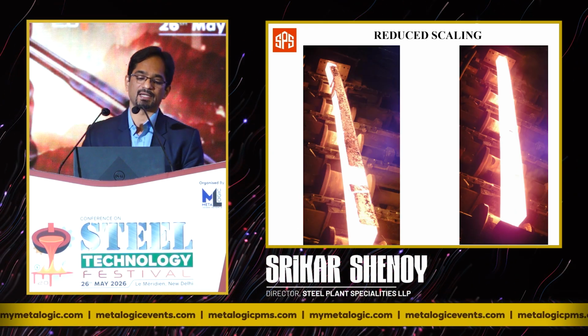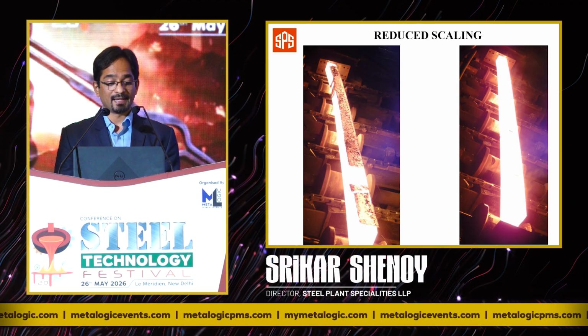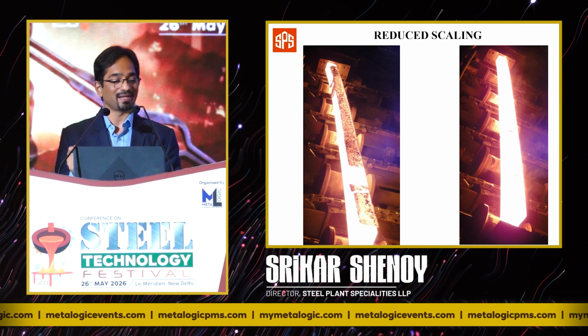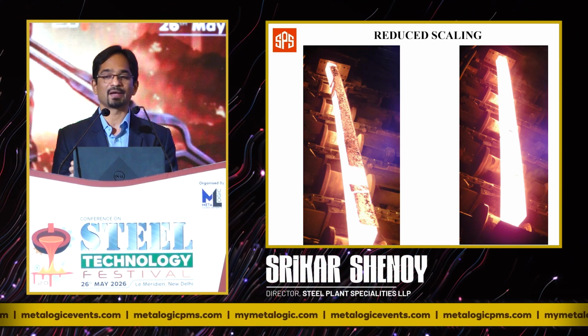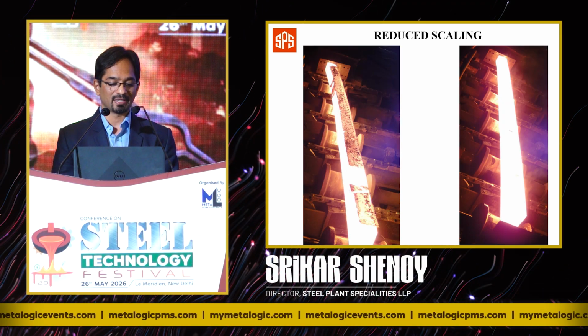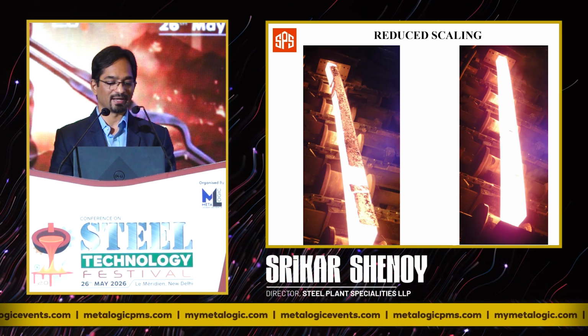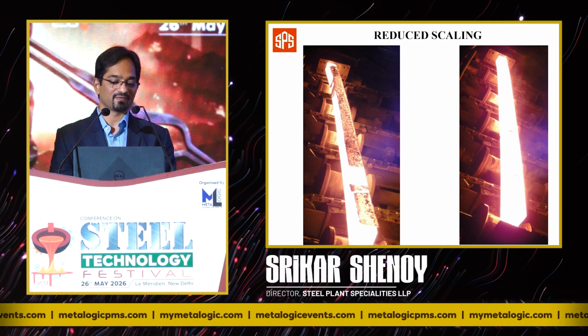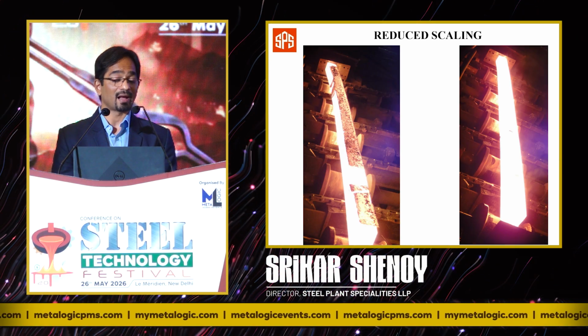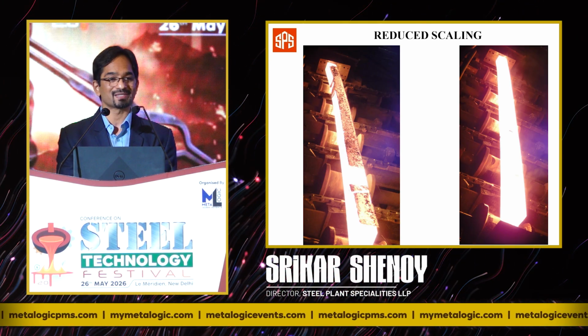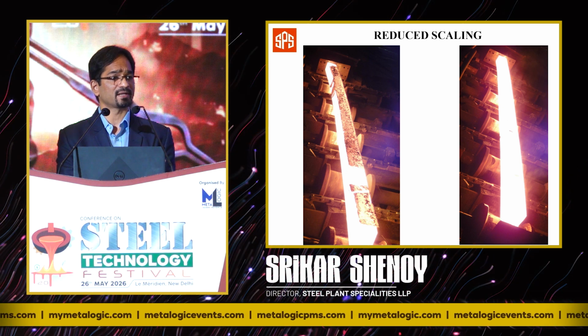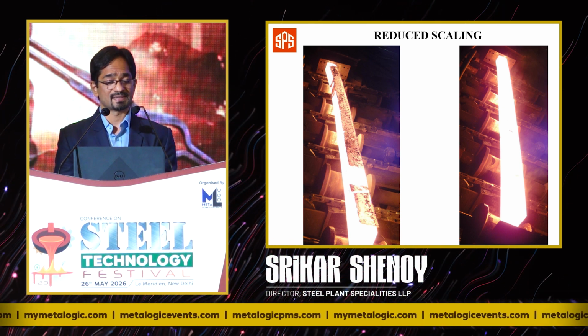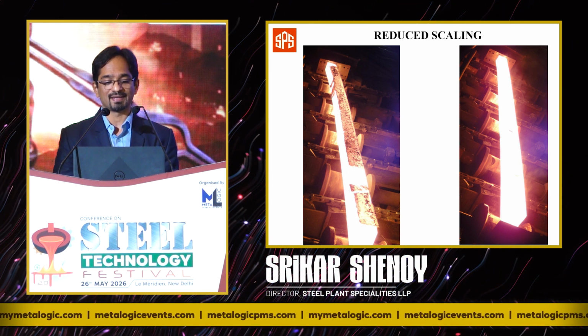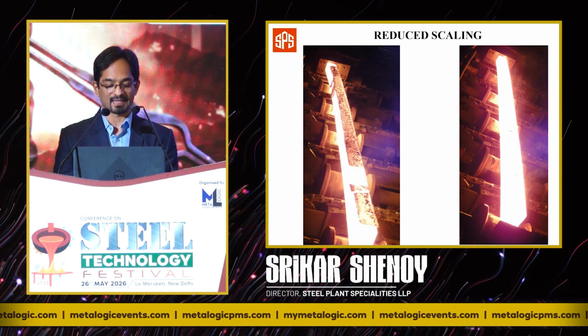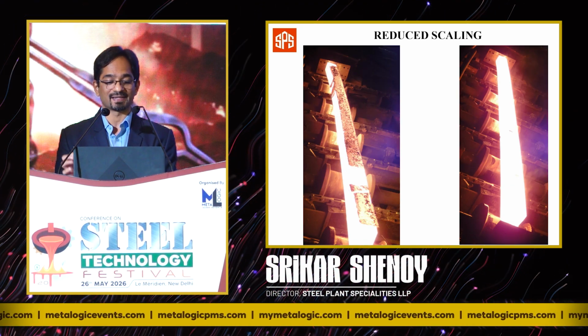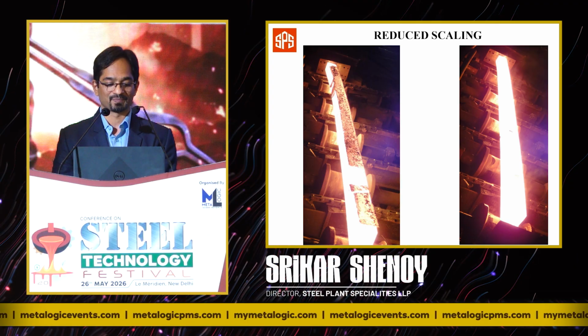This is a case study of nickel steel, which generates very sticky scaling. In spite of having a very good descaler, the image that you're seeing here to your left, you still have scaling on the billet after passing through descaler, because it is very sticky scale. In the same furnace, by use of coating, the same descaler at 200 or 220 bar is able to effectively remove the scaling, simply because the scaling is reduced by around 58%.